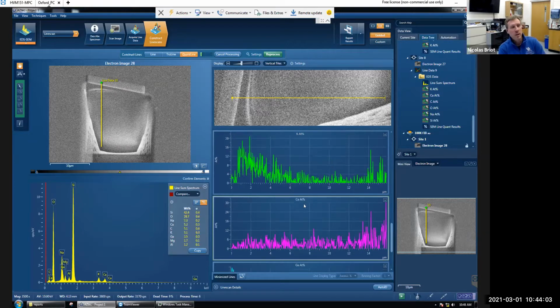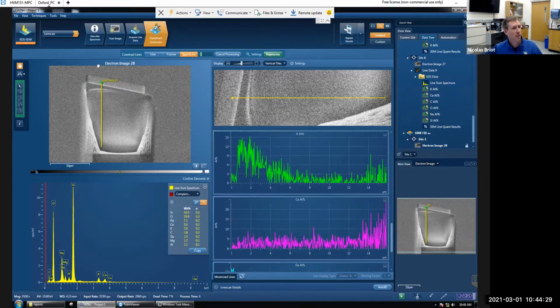So I guess that region that we looked at on the one that was mechanically prepared, I guess that's interesting because we went to a few spots and some spots didn't show much, but we found, I think I remember 2 spots that showed like 5, 6 microns. So it seems to agree well here. It's always good news when things agree like that. But here, because again, I coated everything around, so you have a little bit better conduction, and I think also it's really undisturbed here, so you can start to see that nice decay.